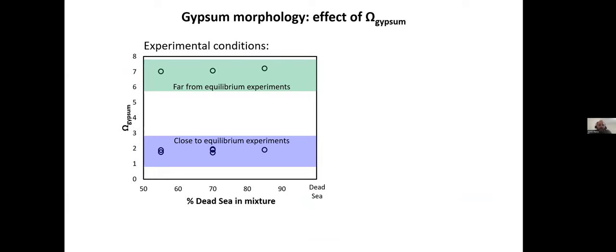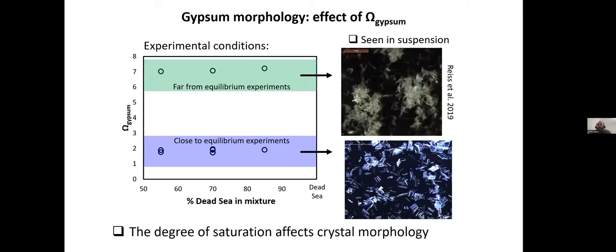And I did experiments under far from equilibrium conditions and closer to equilibrium conditions, changing the oversaturation. And one thing I saw is that far from equilibrium, the crystals have what's called a stellate or spherulitic morphology. Basically, we have a radial center from which crystals grow radially outward. And these crystals were seen in suspension. That means they can stay afloat in the brines. And closer to equilibrium, we get very well-defined idiomorphic crystals. So the degree of saturation has a very strong effect on the morphology of the crystals. And again, the spherulitic morphology I've seen in suspension in these experiments.